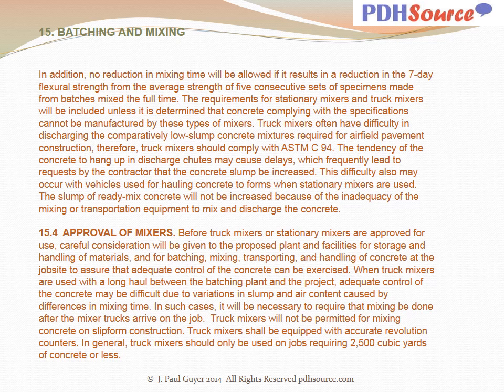When truck mixers are used with a long haul between the batching plant and the project, adequate control of the concrete may be difficult due to variations in slump and air content caused by differences in mixing time. In such cases, it will be necessary to require that mixing be done after the trucks arrive at the site. Truck mixers will not be permitted for mixing concrete on slip form construction. Truck mixers shall be equipped with accurate revolution counters. In general, truck mixers should only be used on jobs requiring 2,500 cubic yards or less of concrete.